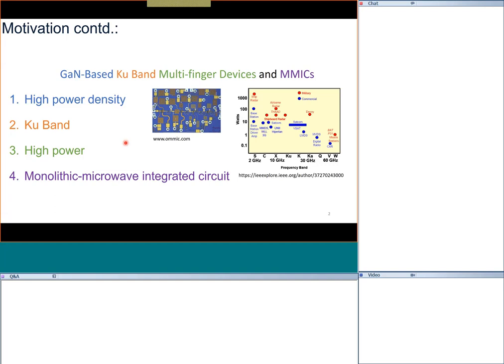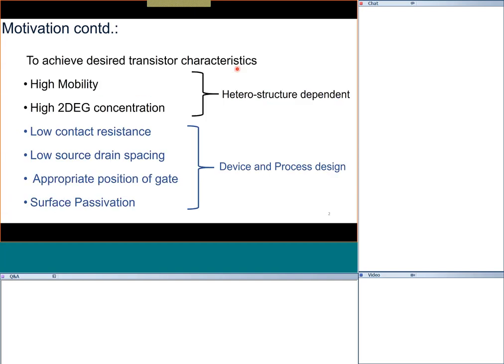These four bullets break down the various aspects of this talk. The heart of the MMIC is obviously the transistor — a high electron mobility transistor (HEMT). Though the name has become a misnomer, we still call them high mobility transistors for historical reasons, but it is actually the high saturation velocity that matters. Additionally, a high two-dimensional electron gas (2DEG) density is important.